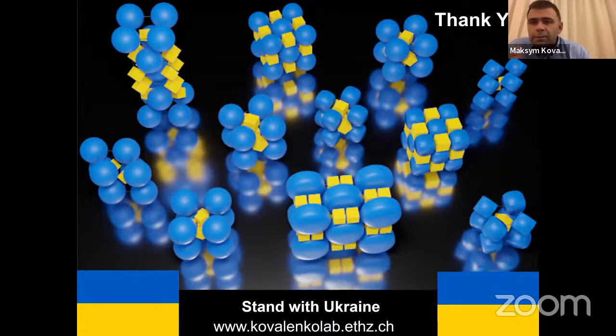Perovskite doped glasses. Another question is from ITAC about the perovskite doped glasses. Very good question. In literature, you're right, there is an increasing number of works where people produce perovskite quantum dots by melting the precursors together with the precursors for the glass. And then when they anneal it, they produce perovskites in the glass, similar to one of the actually very first examples of quantum dots in the history 40 years ago. So this is indeed a very good idea.